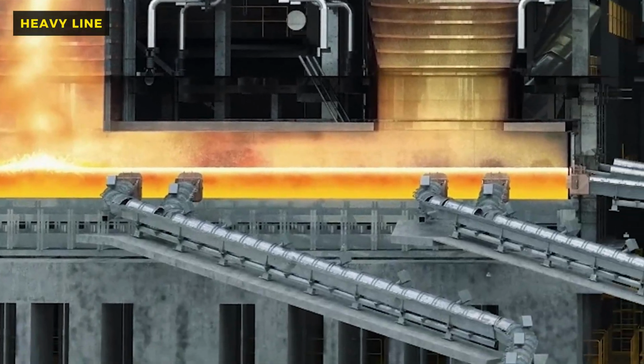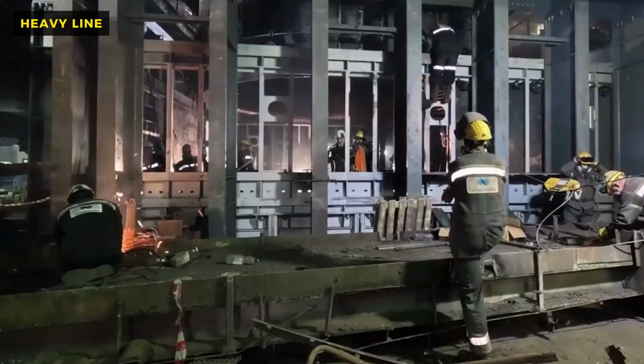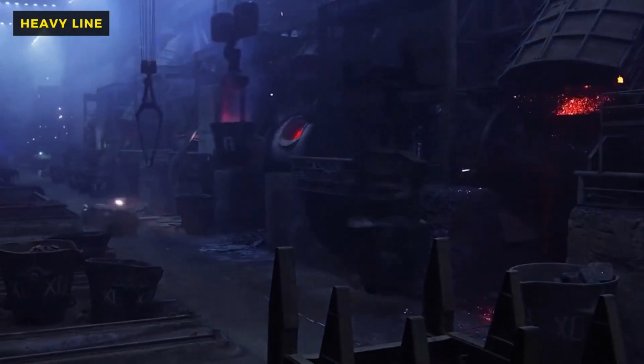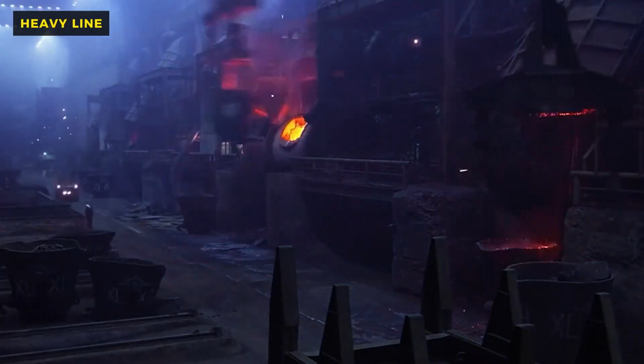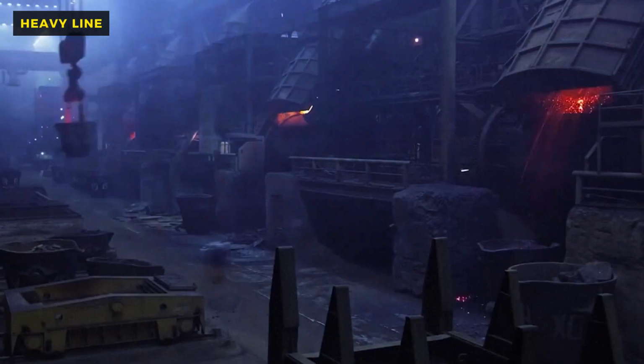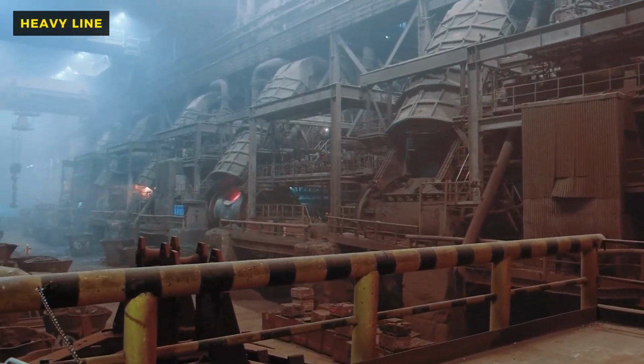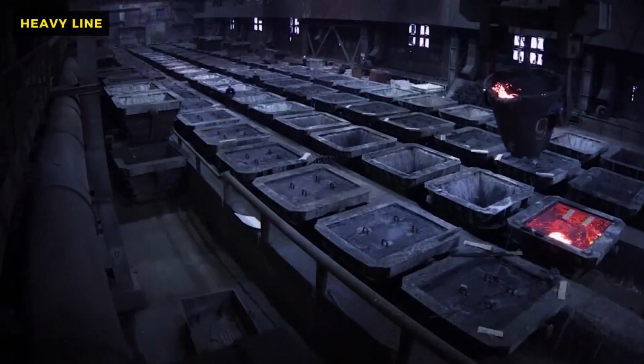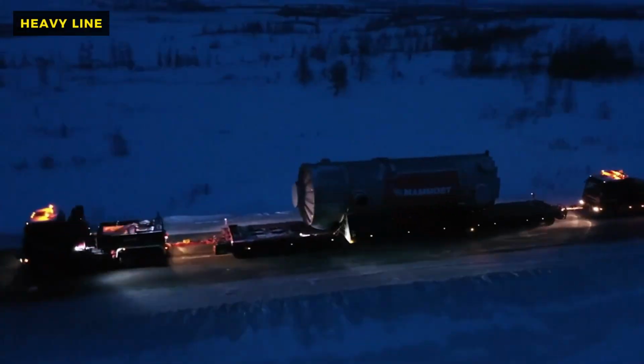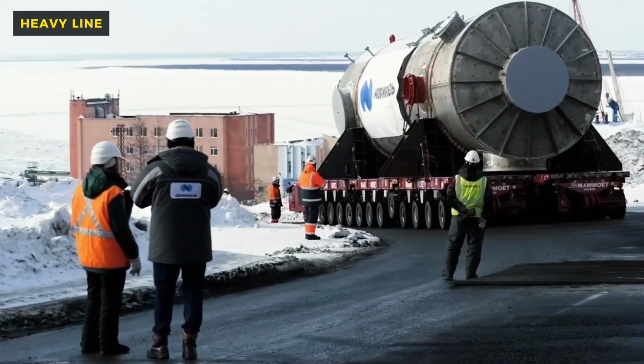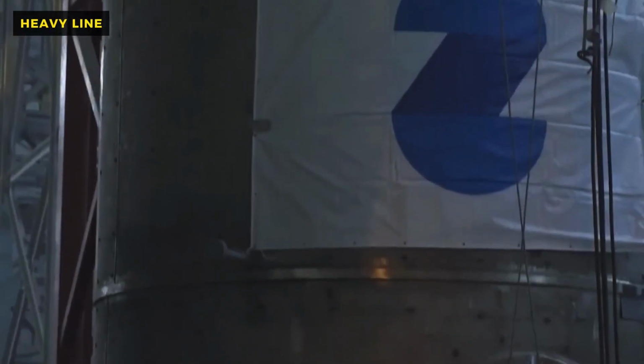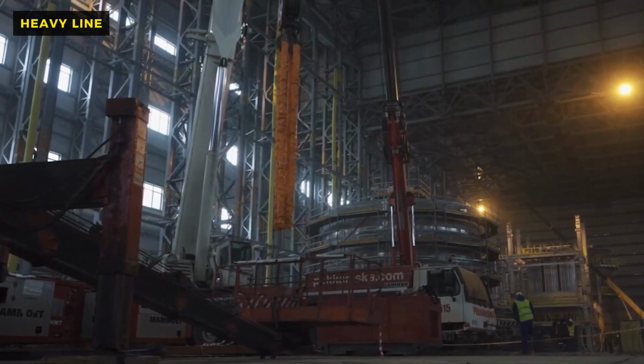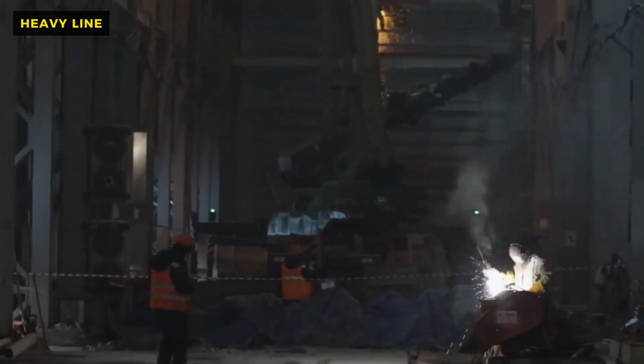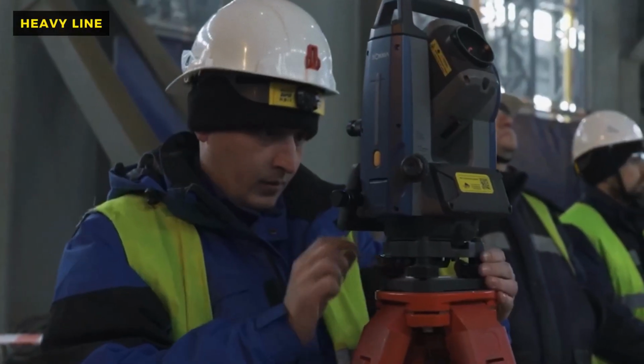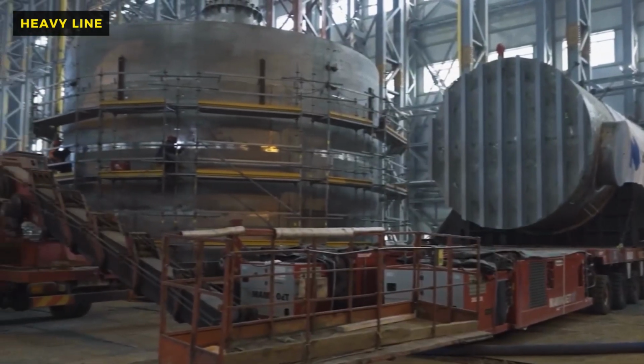This separation is purely physical, reliant on density differences, much like oil floating on water, but the fluids involved are white-hot and viscous. The engineering challenge here is maintaining the refractory lining of the furnace. The bricks lining the vessel are subjected to thermal shock and chemical attack from the corrosive slag. To prevent the furnace from eating itself, the walls are cooled by hundreds of copper cooling elements, or staves, through which water circulates at high velocity. If a cooling pipe were to burst, water would hit the molten bath, expanding 1,600 times in volume instantly, turning the furnace into a bomb.